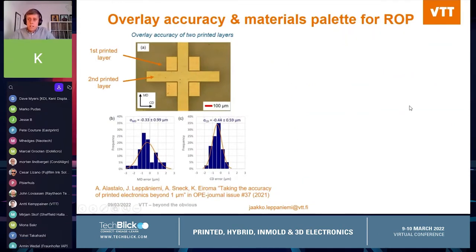Next, I will introduce two critical aspects that enable a wide range of applications in flexible electronics for high-resolution reverse offset printing. First, the overlay accuracy between two layers is critical for multi-layer structures and devices such as thin film transistors. Our ROP system has an automated camera-based registration system for both printing plate and the substrate stages. Here we have data for overlay accuracy between two printed layers in one sample. In this test, after printing of the first layer, the sample was removed and the nanoparticle ink was cured, and the sample was then installed back for the second layer of printing to emulate the real process conditions. You can see that the overlay accuracy is at 2 micron level with a smaller variation in the cross direction than in the machine direction.